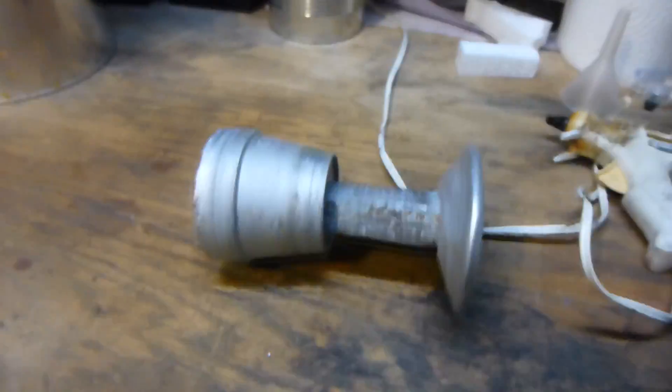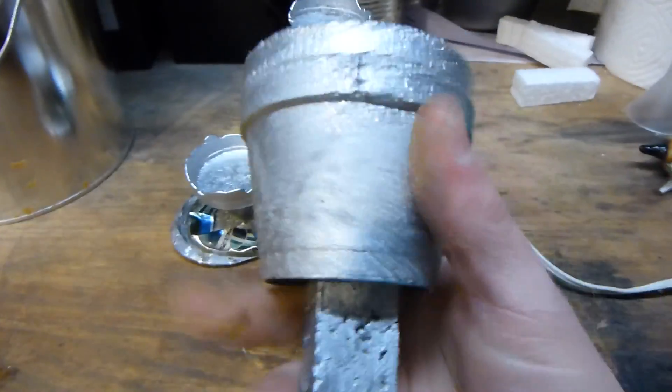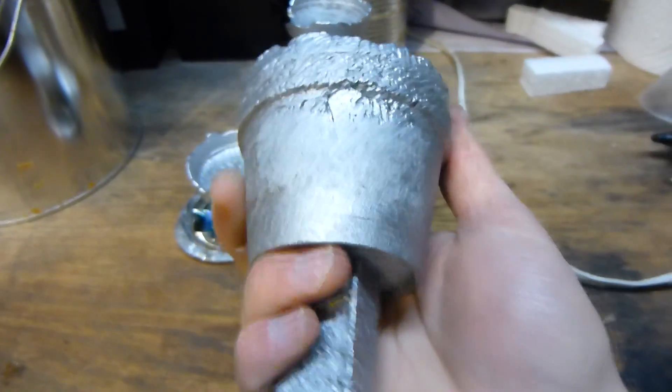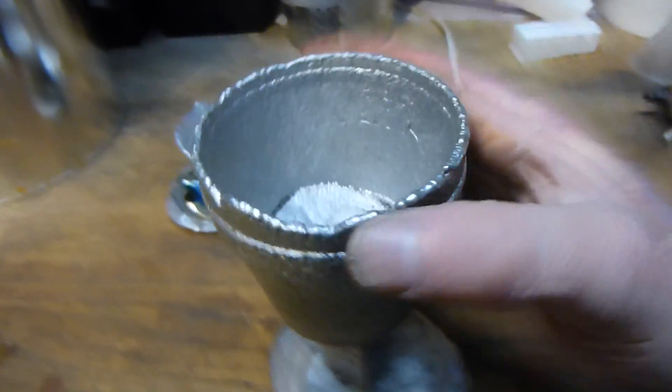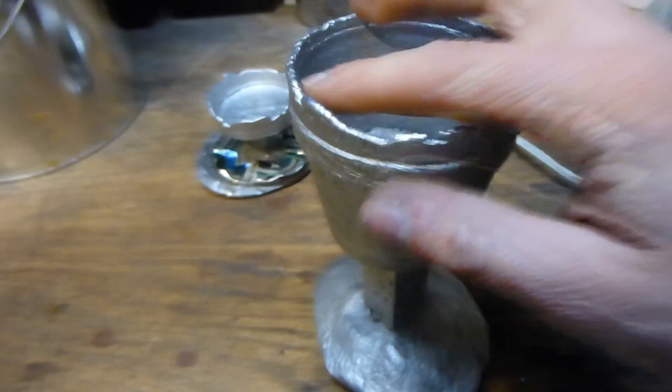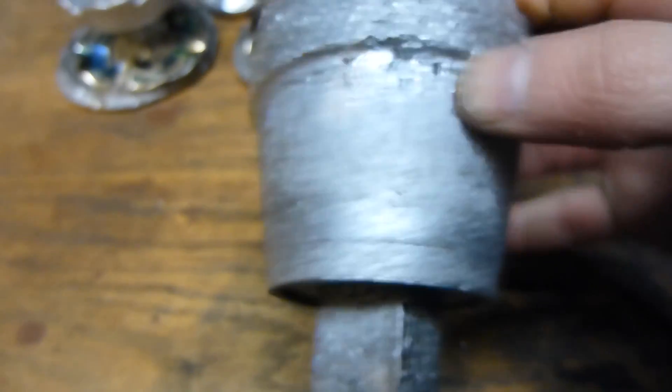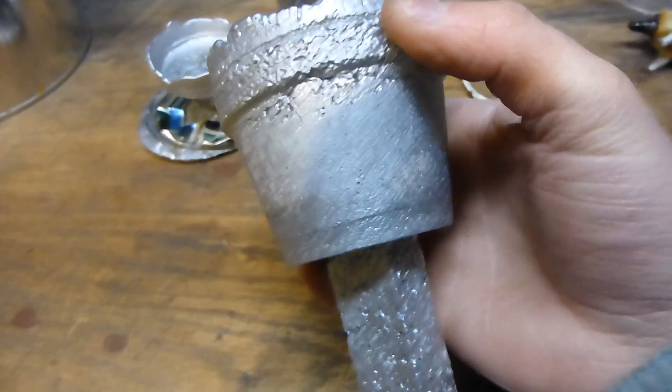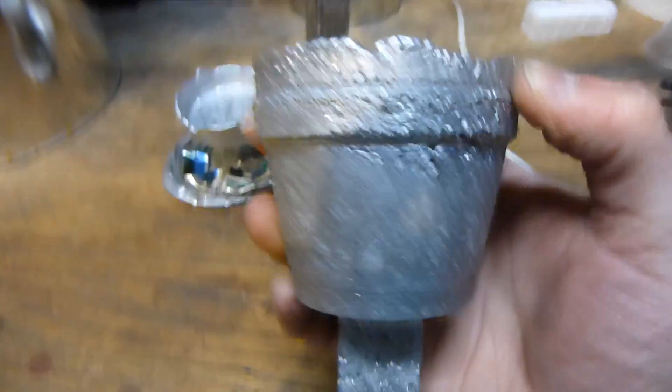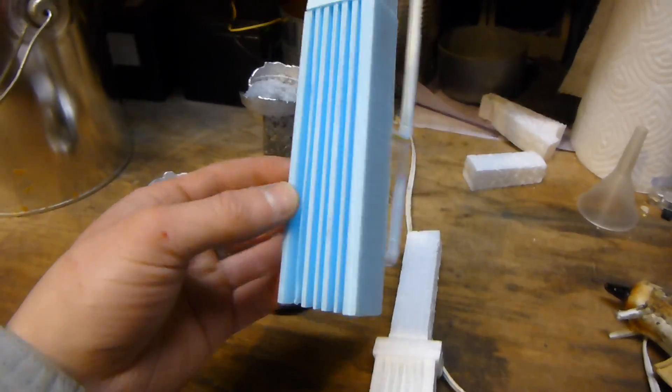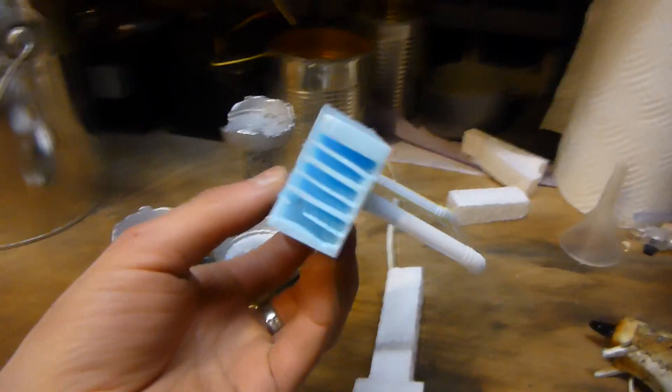Alright, well this one that was double cups worked the best. Here's the other ones, as you can see these ones didn't work very well, but this one pretty much worked except for this area here looks kind of bad. So maybe if I had some vents rather to get rid of some of the gases, that might help.